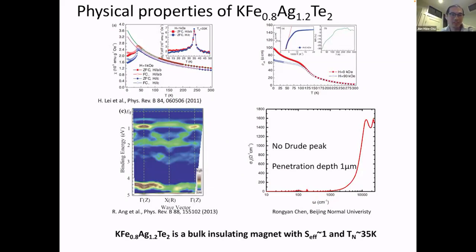I know Johanna has raised her hand, but can I quickly follow up on the resistivity? Since the resistivity is actually measurable at the temperature of the nematic transition, did you try to measure the resistivity anisotropy and see anything from that? Yes, we tried, but we did not really see any clear signature. One possibility is that the resistivity, dominated by a very small activation gap, may not be intrinsic to the gap. Maybe it's due to some defects or some extrinsic behaviors, probably a hopping type of conduction, some in-gap states. Right.